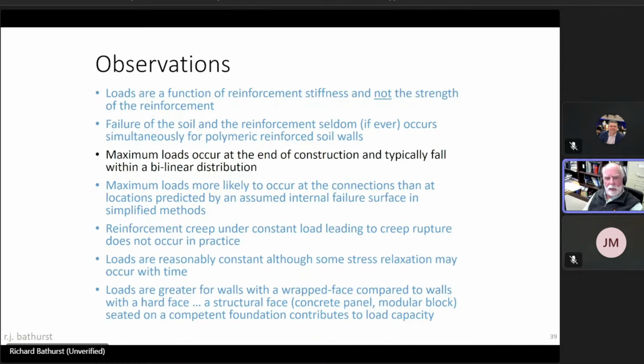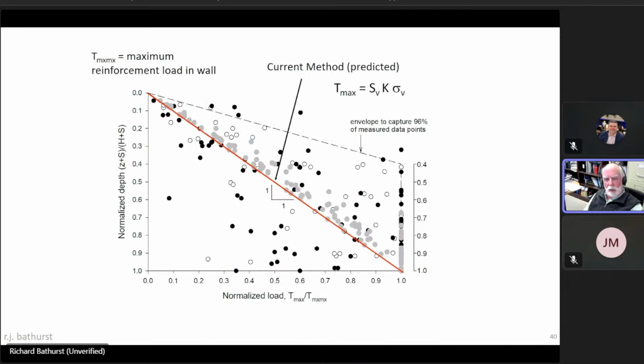Another observation is that we found that the distribution of maximum loads in the reinforcement layers was typically not linearly increasing with depth. It was usually bilinear. We demonstrated this by taking all of the measured loads that we had recorded in full-scale field walls and plotting them on this normalized plot, where the horizontal axis is the maximum load in a reinforcement layer divided by the maximum load from all instrumented layers, and on the vertical axis is the normalized height of the wall.